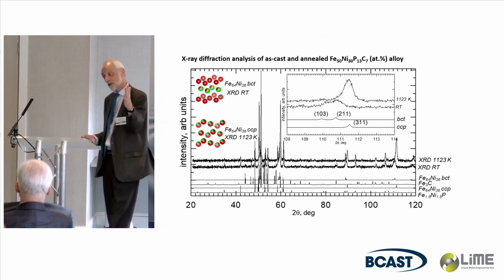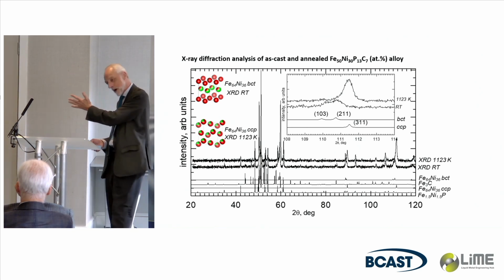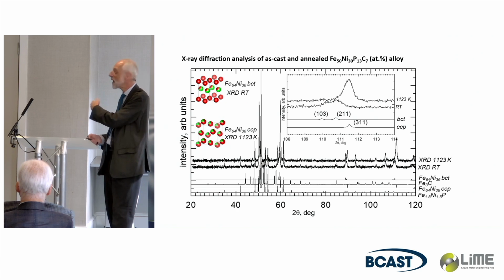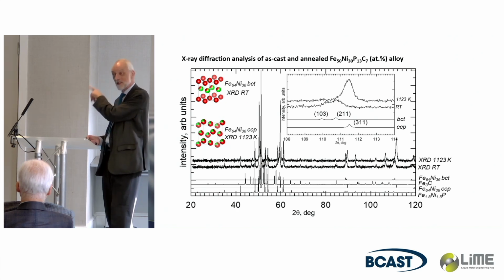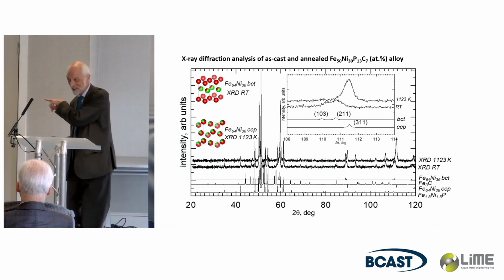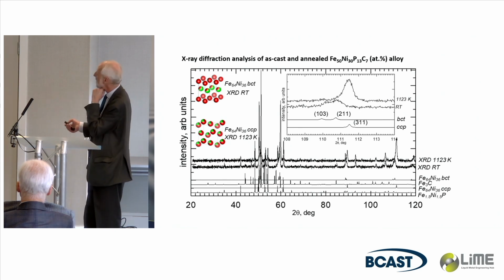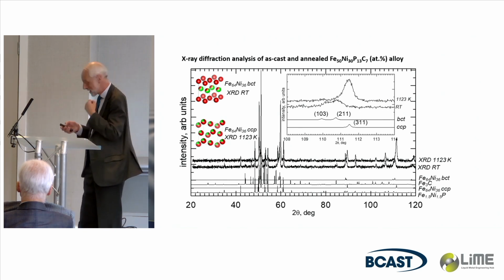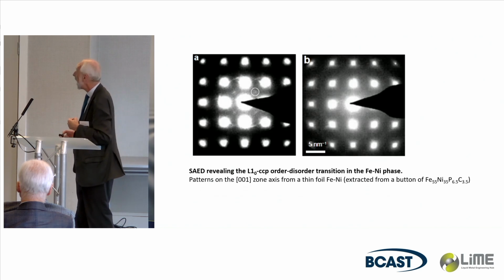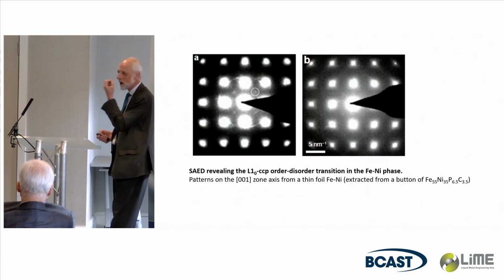But if you go to different X-ray wavelengths to be able to go up higher in the Q scale, the equivalent peaks at higher angle are not split, as they should be. So I don't think this provides us with evidence for tetrataenite after all. And this I thought was our surefire thing.